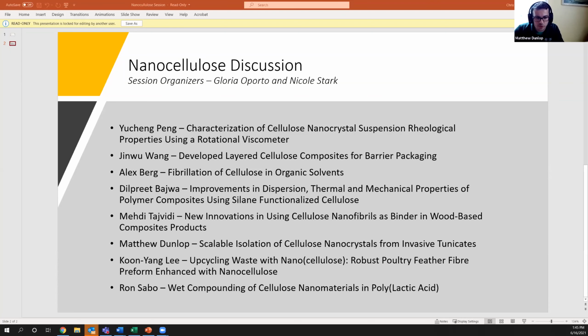Gotcha. Based on the dry weight, we're talking low percent. How should I put this? We measured a number of different ways. If you're looking at 200 kilograms of wet raw tunicate input, you would expect to get 1 kilogram of dried tunicate CNC. Now, the CNCs are generally never dried, and we prepare them as a 1% suspension after filtering out the salts and such from hydrolysis. And so as a result, you end up getting about 100 kilograms of 1% CNC suspension from 200 kilograms of raw tunicate input. So two different ways to think about it, but that's our yields, more or less.